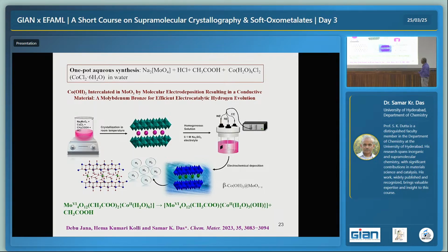Then to find out why it is such a good catalyst, we found that the material is not anymore just a mononuclear cobalt compound. It has become cobalt hydroxide. That means beta cobalt hydroxide intercalated between the MoO3, and that is now the catalyst for HER, hydrogen evolution. Now you may ask me a few things. We are doing electrocatalysis at low pH, no? pH 3.84. I told you, organic acid. And that is making cobalt hydroxide.